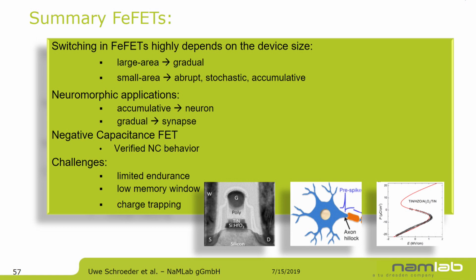That's a good question. If you look at the behavior of the devices, if you look at your USB stick, there you also have only the possibility to switch it between the two different memory states like 10,000 times. So that's very similar to the 10^4, 10^5 cycles we showed for the FeFET case. On the other hand, there's one thing, and that's one of the discussions we're currently having. I showed this sub-threshold voltage switching behavior we use for the neuromorphic application. If you think of an array of 1 transistor memory cells in the array,